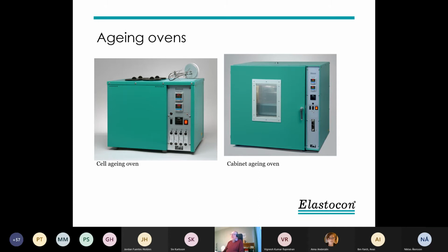Then we designed a cabinet aging oven, and that is more difficult, to get a good temperature uniformity in the whole space. And on these 5 ovens, we did a lot of measurements.